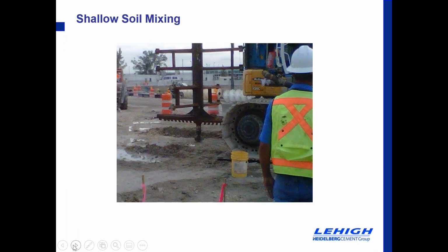So this is a great picture of the tool itself. So think of it this way. You know, the ground was there, nothing was done to the ground. The contractor shows up on the ground site with this particular tool, which is a large cutting tool, which he then drives into the ground hydraulically, and then running down the center of the tool is where we put the slag cement, bentonite, and Portland cement mixture. Then the tool reaches the target depth. It then reverses out as it is mixing that cementitious material in. And the real issue when we started this was, well, what should that mix look like? Next, please.